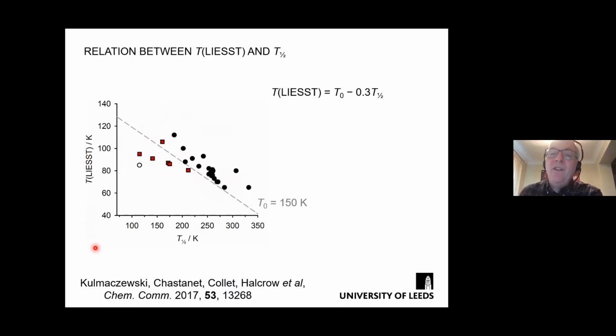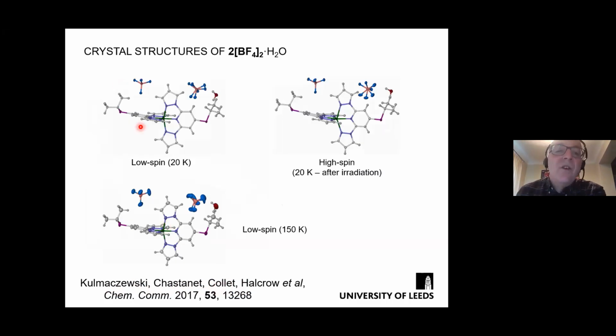So to try and understand this, we did some crystal structures. We sent crystals of 3 of these compounds to Rennes, to Eric Collet's lab, and he very kindly measured them for us. The first one he measured was this one. So this is the low spin and the high spin at 20 Kelvin before and after irradiation. And they look completely normal. There is nothing unusual about these compounds. And even the disorder we see in this anion at 20 Kelvin is still kept, as in the 150 K low spin structure, for example. So there is nothing unusual there.